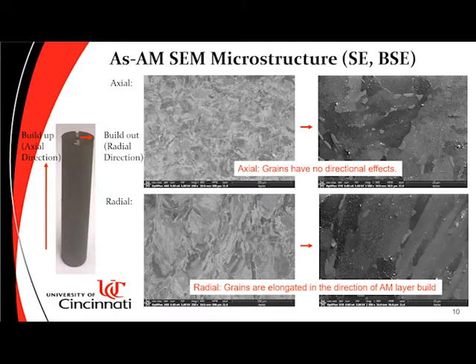Going back to the as-manufactured SLM samples, the SE and BSE images show that in the radial direction, the grains are elongated in the direction of the AM build direction, whereas in the axial direction, the grains have no directional effects. XRD results also show that the sample has almost full FCC structure with some sigma phase at the grain boundaries and finely dispersed carbides in the grain and also at the grain boundaries.